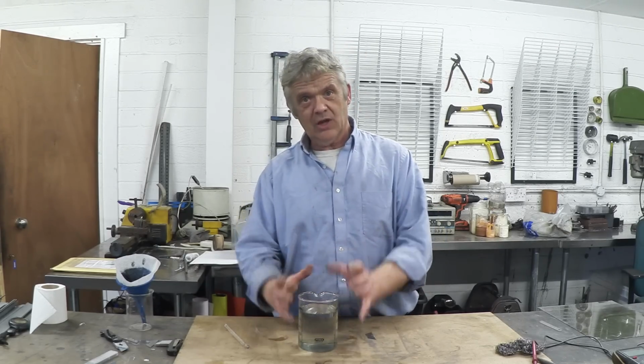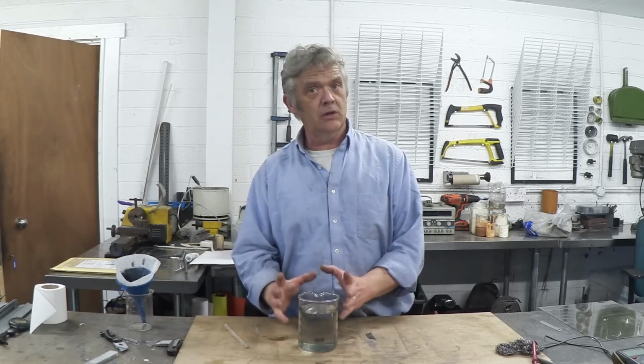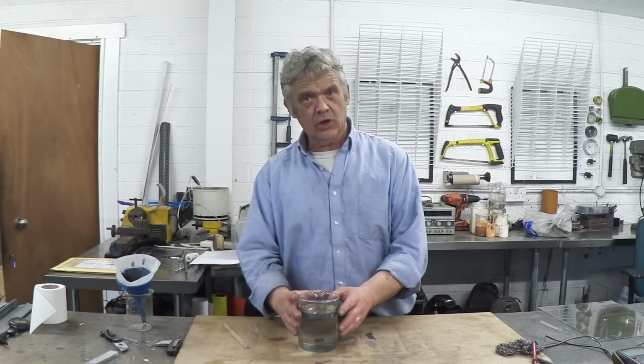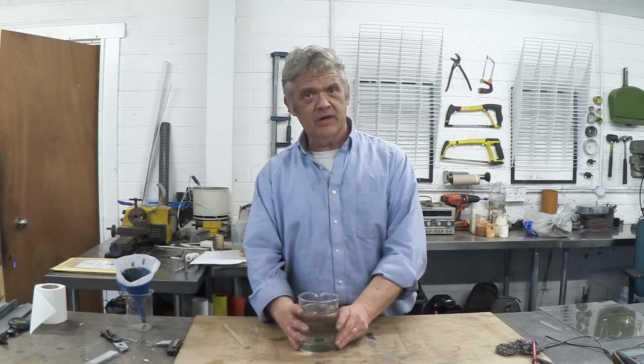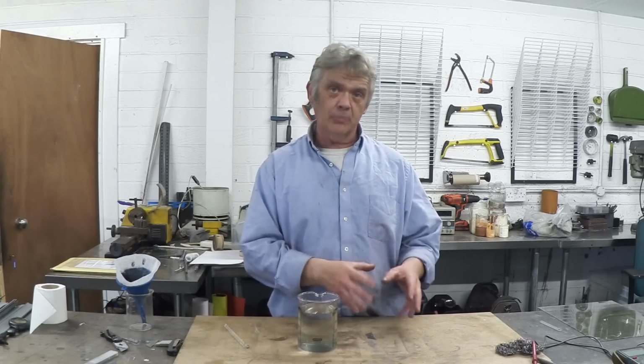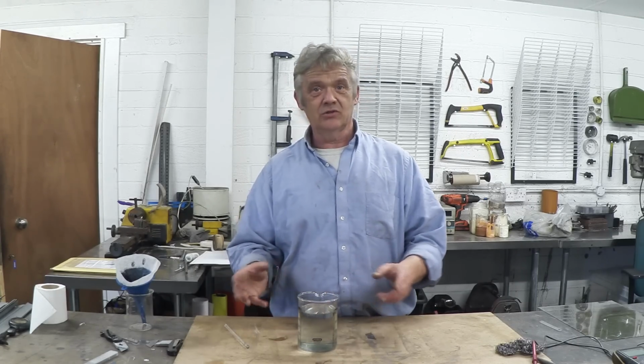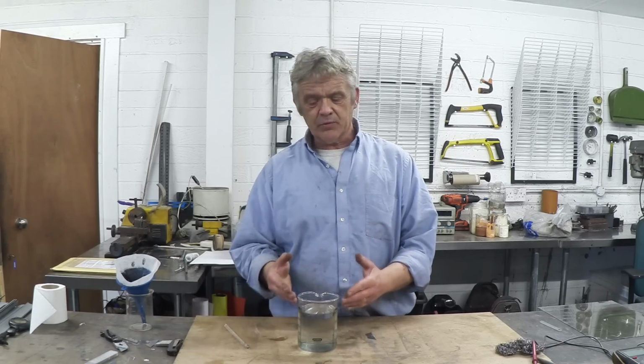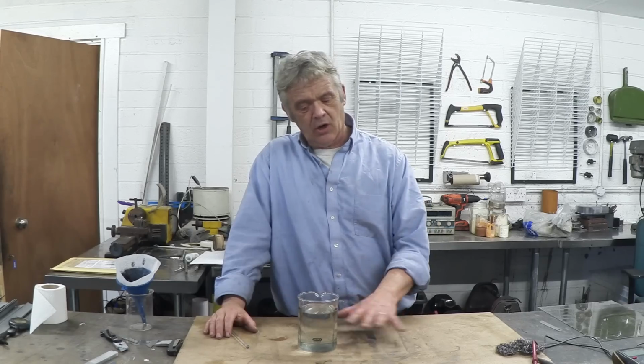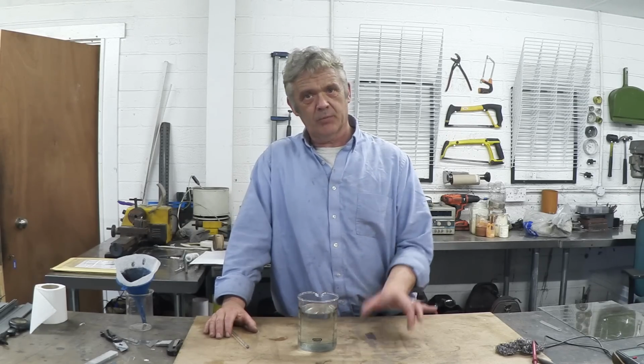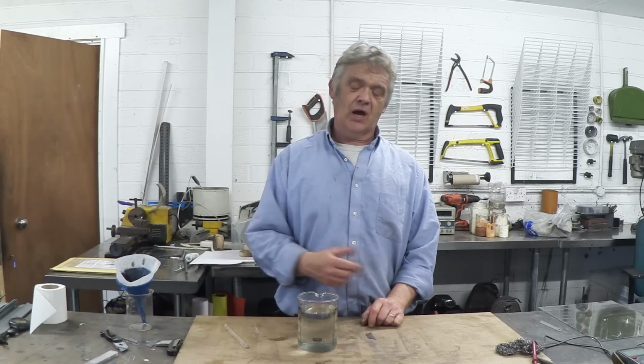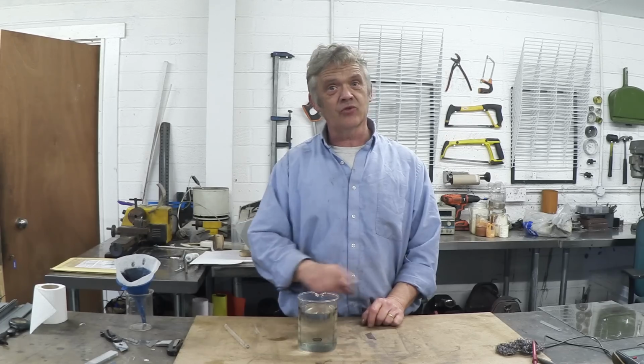We've also recovered the indium, which itself could be an entire business. And then once we've recovered that indium, what we need to do is obviously coat it onto some of the optical glass to make yet another kind of conductive glass that can be used in solar cells. Now, the process of covering this in indium tin oxide is really quite simple, actually. You get a hot plate at 400 degrees centigrade, pop your glass on there, and then use an airbrush and spray this liquid onto it, and it will just burn off, leaving you indium tin oxide.